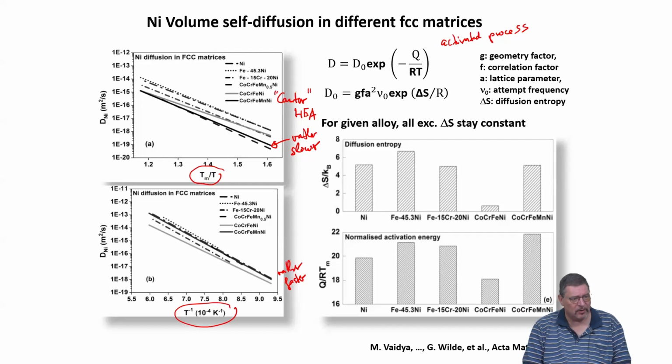Theoretically, normally, it's also related to the lattice geometry as well as the interactions between the different atoms and also between the vacancies and the different atoms. So this is a term from which you can estimate the vacancy interaction or the vacancy binding enthalpy of the different species. In experiment, it's difficult.